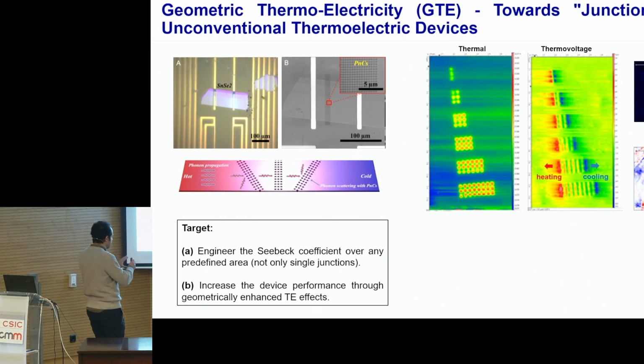Here you see a thermal map. Let me first explain what we see here. You see a thermal map of the patterns that we create with the holes. In this case, the thermal conductance contrast between our patterns and our substrate is very well defined, as you see, with a very different color inside the holes. However, in the thermovoltage, you see the thermovoltage spread around the holes by a few hundred nanometers.